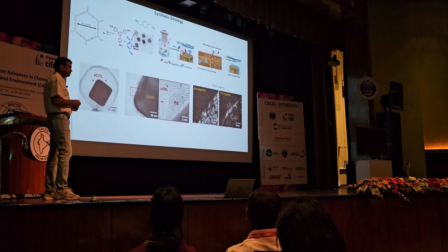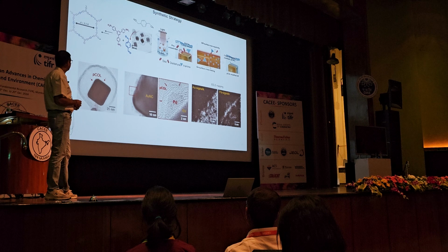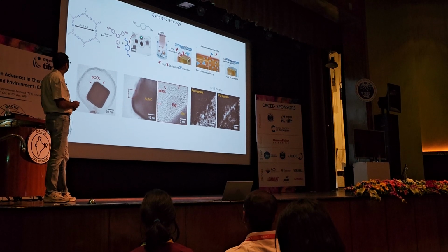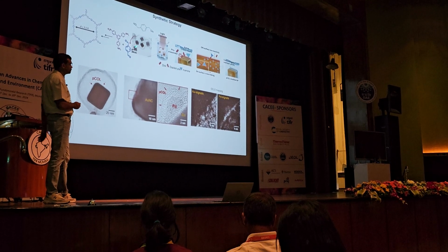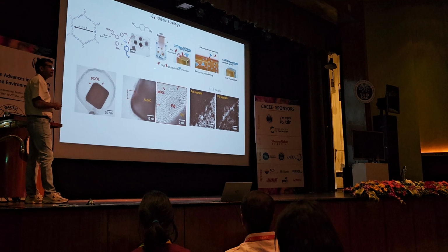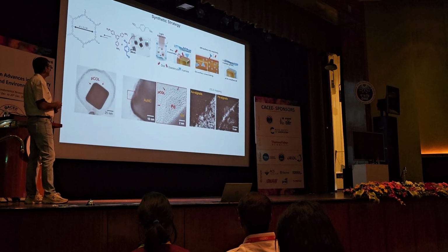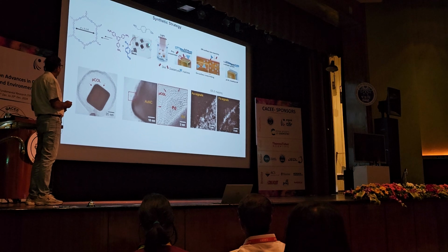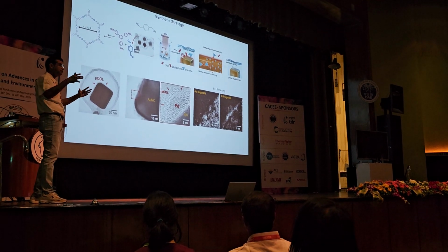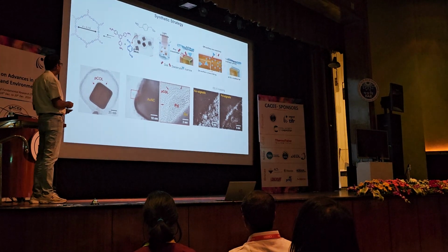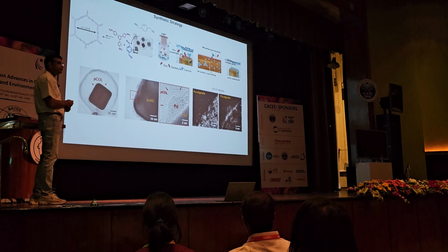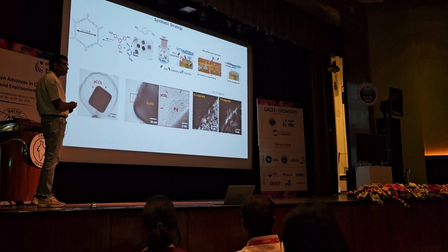As far as synthesis is concerned, we start from, for example, any plasmonic nanocrystal you can choose, which you can synthesize in homogeneous sizes, and encapsulate them in a hollow silica shell. Why a hollow silica shell? That stops them from aggregating, and without any ligand or surfactant, you can disperse them in solution.